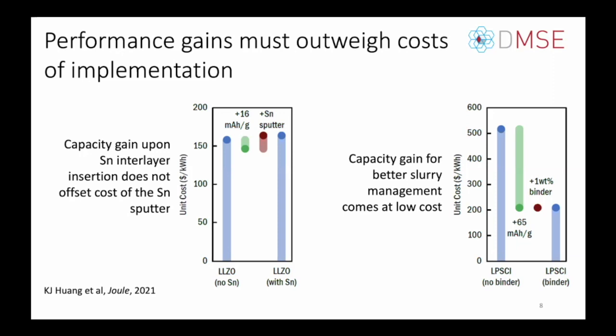And so I just picked two examples here, combining the techno-economic work I said with the data mining to look at what are the potential scaled implications of strategies that have been pursued. And I'm comparing two different strategies here that have been pursued to address interfacial issues and the particular recipes associated with those strategies. So in the first example on the left-hand side, there's a sputtered tin layer to help with interfacial resistance performance. We see the baseline cost in blue there, where we don't have the added tin, with a performance increase of about 16 milliamp hours per gram as reported.